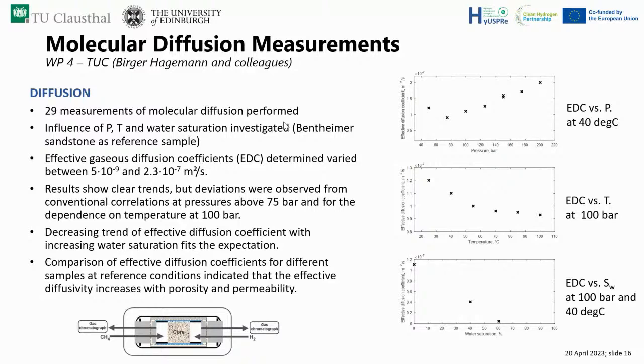So it's clear that if you compare the effective diffusion coefficient for different samples at reference conditions, it indicates that the effective diffusivity increases with porosity and permeability. And you see that also in the graphs on the right. This is for the Bentheimer sandstone reference sample here. Shown is the effective diffusion coefficient dependence on pressure, temperature, and water saturation, to confirm what we found on the left.